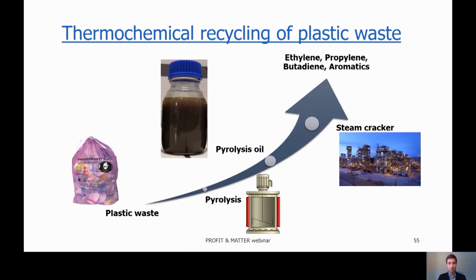We can start with plastic waste, for instance from the P+MD bag, which goes into a pyrolysis reactor used to crack the plastic waste to produce a pyrolysis oil, which can be seen here on top from real waste, so it's quite dark and viscous.